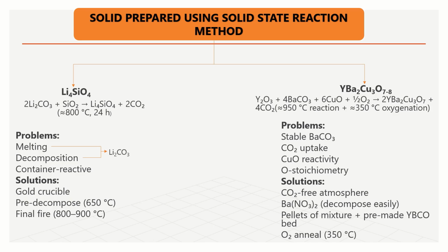And copper oxide reacts with many container materials at high temperatures, and a high temperature is the requirement for the reaction to occur. Also, the product YBCO has variable oxygen content. So the oxygen must be exactly correct, otherwise the superconducting temperature drops.